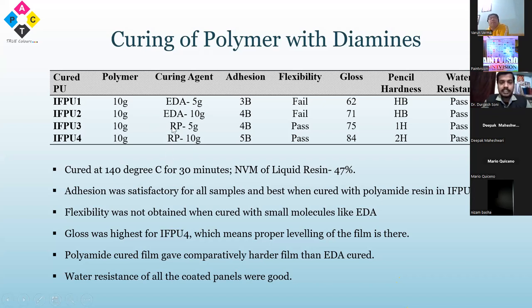Reactive polyamide, we can see that it is a polymer having NH2 groups at terminal, that is amine groups at terminal. So when it reacted with our polymer, good results were obtained in adhesion, flexibility and gloss also. Pencil hardness was also 2H and all the films which were cured with the reactive polyamide passed the water resistance test. So we got a somewhat better result when we cured with reactive polyamide.